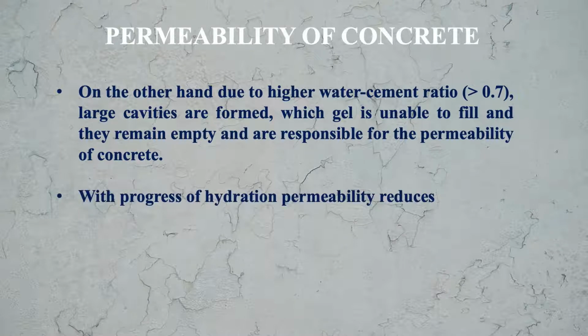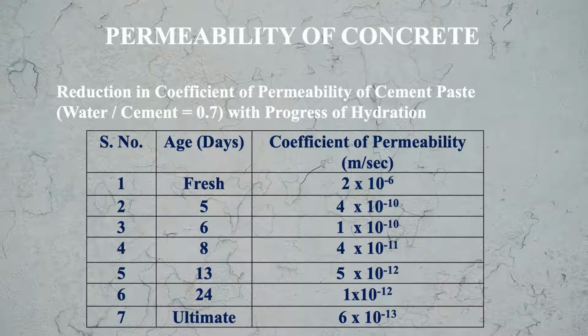With progress of hydration, permeability reduces. Here in this table, you can see the reduction in coefficient of permeability of cement paste when we are taking the water cement ratio as 0.7 with the progress of hydration. If we take the fresh concrete, in second column you see the age of concrete in days. So if we consider the fresh concrete, then coefficient of permeability measured in meter per second is 2 into 10 to the power minus 6 meter per second.